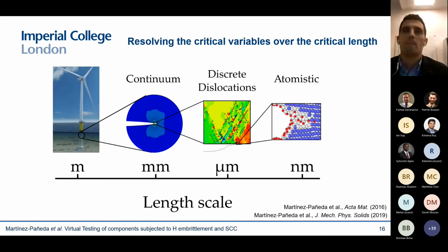So let me elaborate a bit more on each of these ingredients or each of these stages of the model. So the first one is related to this crack tip mechanics, or resolving the critical variables over the critical length. And there's always a trade-off here, of course. So we want to be able to tackle engineering problems, so we want to use what we call continuum models. However, we also want our predictions to be reliable, so we need to resolve the physics. We need to capture the physics to trust our predictions. And if all the magic is happening in the first 3 atoms ahead of your crack tip, then you need atomistic resolution to resolve your problem.